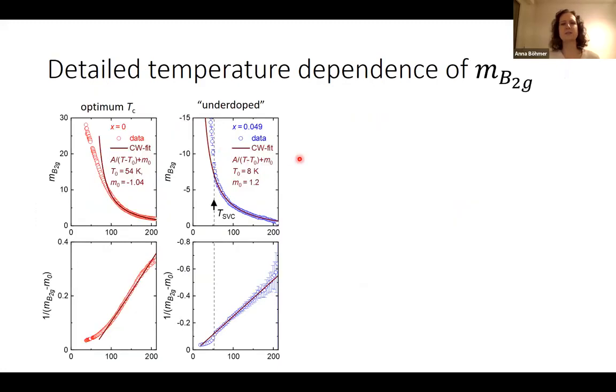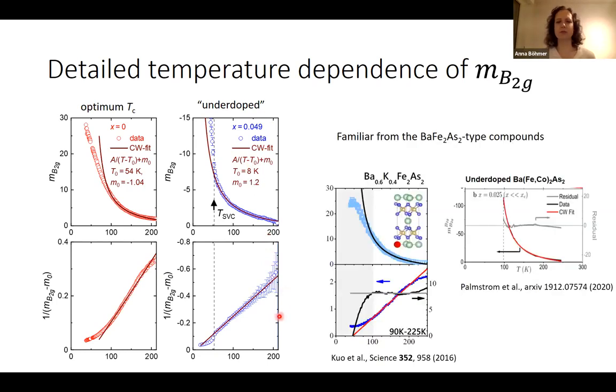And as is customary in the field, I tried a Curie-Weiss fit. For the optimum Tc sample, the undoped 1144, well, Curie-Weiss is approximately working, but there are strong deviations, especially at low temperature. For the nickel-doped one, which would correspond to an underdoped 122, there's a beautiful Curie-Weiss law that works very well. So again, this is reminiscent and familiar from what we know of the 122 compounds. This optimally hole-doped barium 122 looks very similar to this optimum Tc 1144, even the way this deviates. While the underdoped 122 show a very nice Curie-Weiss law down to their transition, same as here. So this is a very, very familiar behavior.